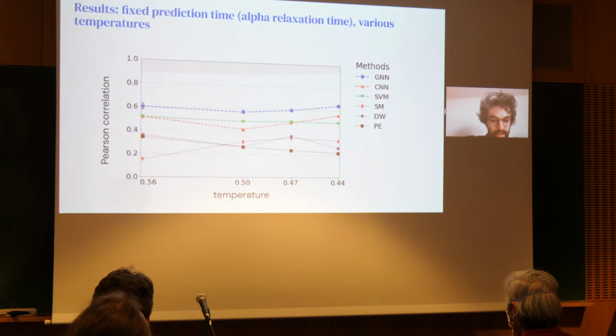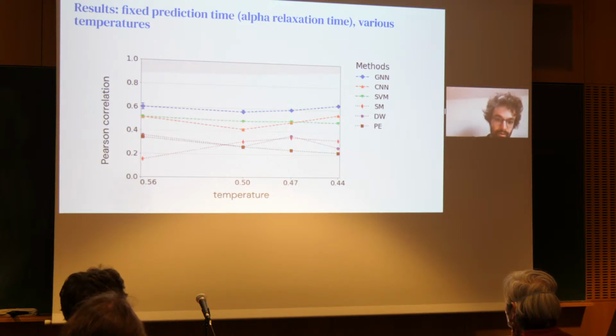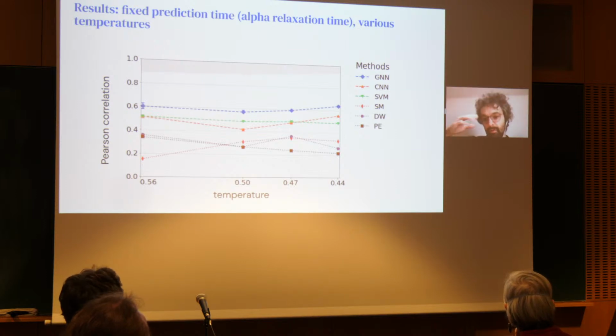And so this is another version of this plot where now we fix the time and vary the temperature. And this again shows that the method can work across a range of temperatures. So these are all temperatures above the mode coupling temperature. The point on the right here corresponds to the previous plot. And again, there is a similar ordering of methods and similar improvements on using a more complex network.